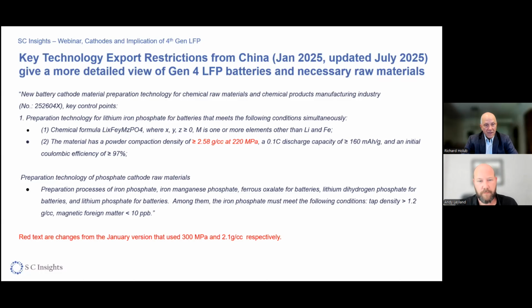And the next part of that restriction is around the iron phosphate cathode raw materials. And you see that there's a list of potential raw materials whose production technology is being restricted. But they specifically call out that the iron phosphate would have the following conditions. All the discussion around particle size is summarized into a tap density here of greater than 1.2 grams per cc, and then also magnetic foreign matter of less than 10 parts per billion.